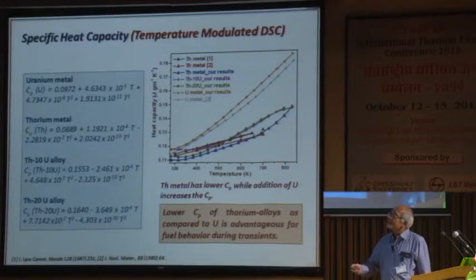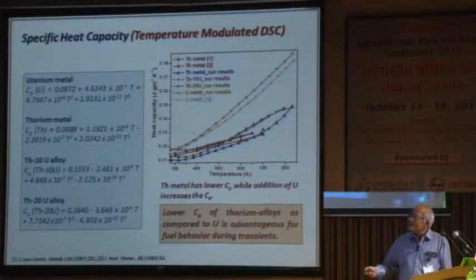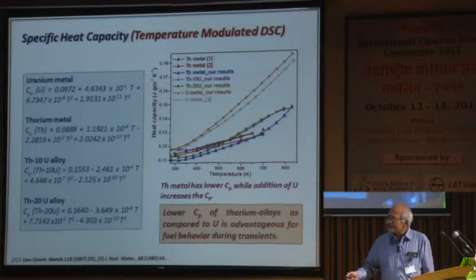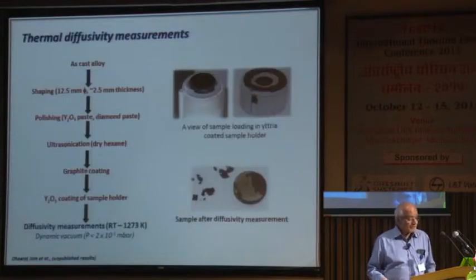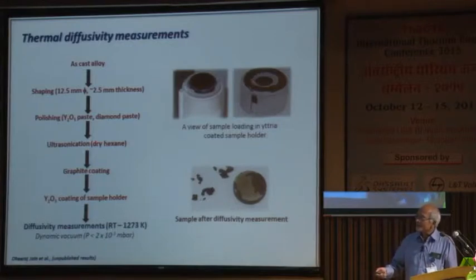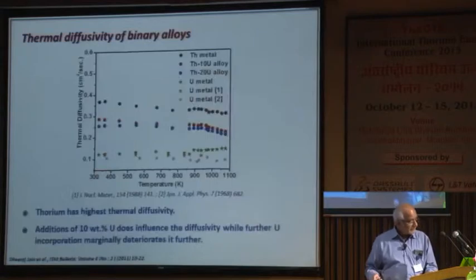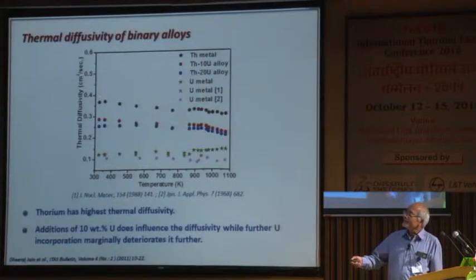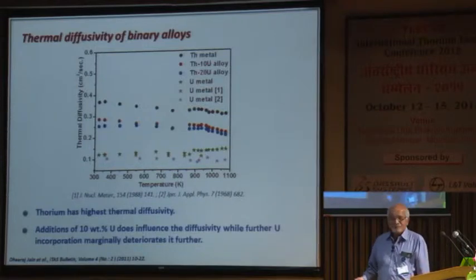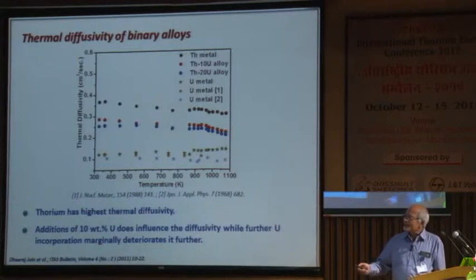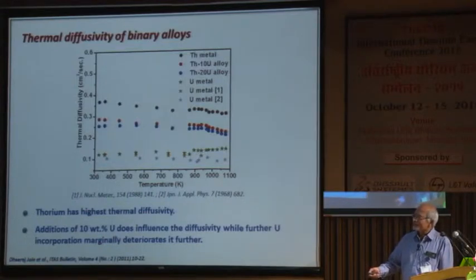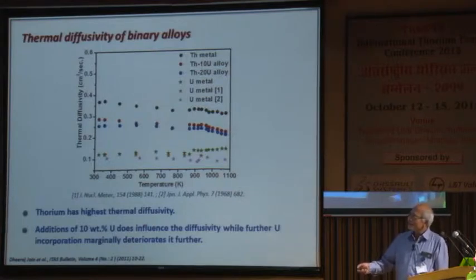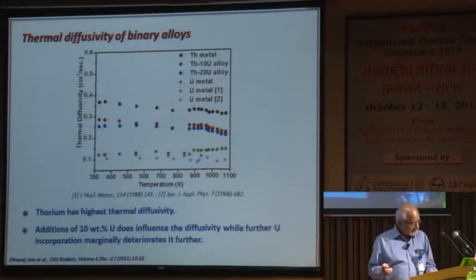The specific heat of these alloys has been measured, and the important point here is that the lower Cp of thorium alloys as compared to uranium is advantageous for fuel during transients. The thermal diffusivity measurements have been done through all this. I will not go into the details. And the final results: here you have the thermal diffusivity for thorium metal, for uranium metal somewhere here, and the blue one is for thorium-20 uranium. So, thorium has the highest thermal diffusivity, and addition of 10 weight percent uranium does influence the diffusivity, but further uranium incorporation marginally deteriorates it further.